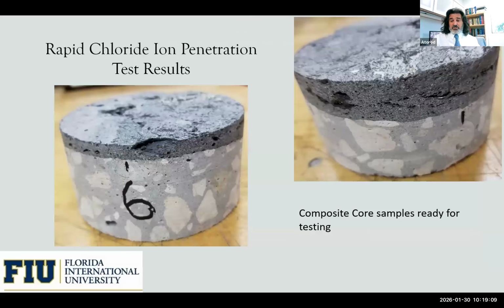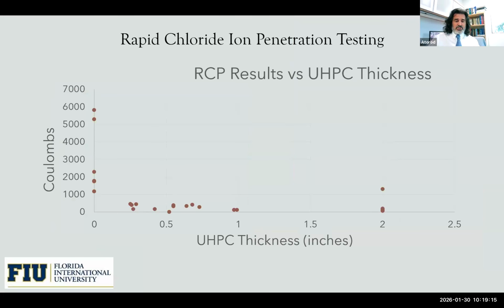We have sprayed UHPC or cast in place UHPC on top of a normal strength concrete. And you can see with the rapid chloride permeability test, which by the way is not a good test for durability because of the steel fibers, but nevertheless, look here. All of a sudden, even if I put a half-inch of UHPC, sprayed or cast in place, the number of coulombs goes very low, below 300 or so.